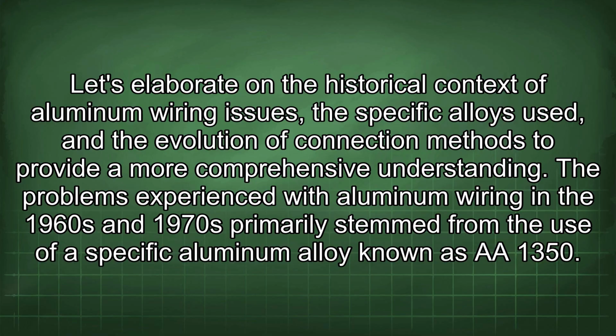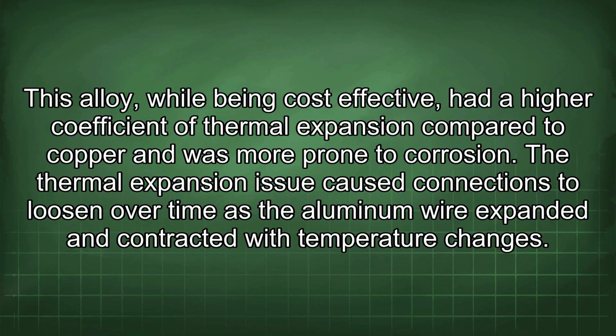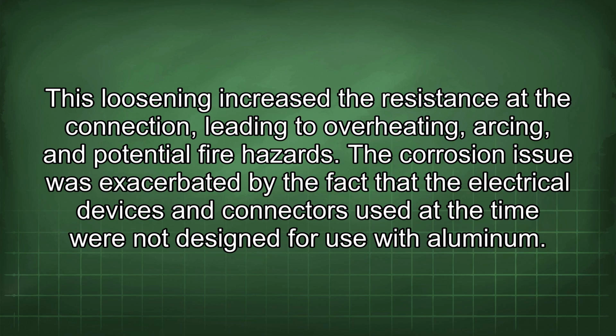The problems experienced with aluminum wiring in the 1960s and 1970s primarily stem from the use of a specific aluminum alloy known as AA 1350. This alloy, while being cost-effective, had a higher coefficient of thermal expansion compared to copper and was more prone to corrosion. The thermal expansion issue caused connections to loosen over time as the aluminum wire expanded and contracted with temperature changes. This loosening increased the resistance at the connection, leading to overheating, arcing, and potential fire hazards.